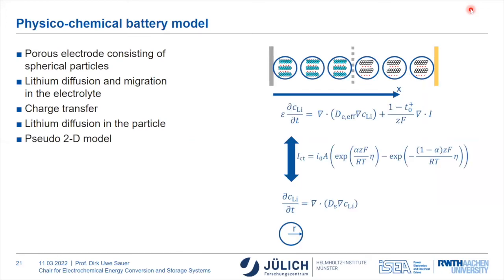And finally, we have a two-dimensional model in this case here. We're operating also three-dimensional models to understand, for example, how lithium is diffusing into a backside layer of an electrode, or from the electrode overhang back and forth into the active material. So all these things, which at the end of the day are responsible for improvements in capacity, which we often see during rest periods in testing of batteries, for example, or even if the batteries just was laying around 2 weeks, 4 weeks or longer, we suddenly have a significant different capacity. And this is not due to aging, but due to activation or loss of lithium into the overhangs or backside coatings of electrodes.